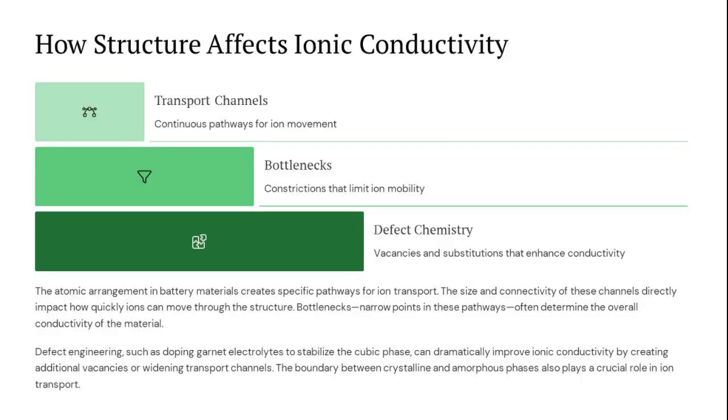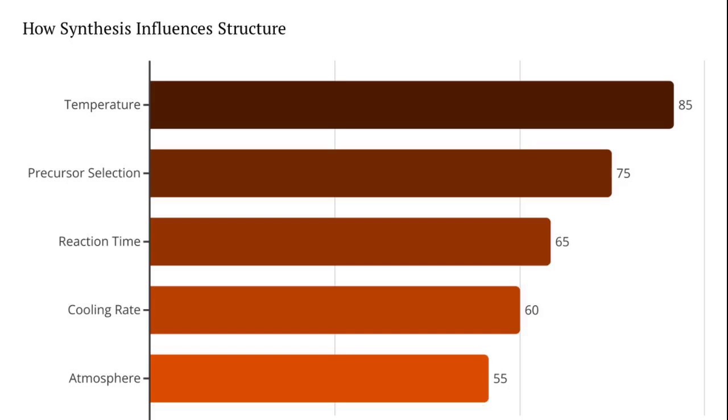Structure-property relationships: how structure affects ionic conductivity. In some studies, researchers have used Sr2+ and Ta5+ with larger ionic radii for co-substitution in the La3+ and Ti4+ sites to increase the bottleneck size in perovskite structures, thereby expanding the average bond length and increasing Li+ ion mobility. How synthesis influences structure: the synthesis methods influence inorganic solid electrolytes in terms of phase structure, ratio of amorphous phases, strain, defects, grain size, grain boundary resistance, impurities, and morphology, thus critically determining their performance in batteries.